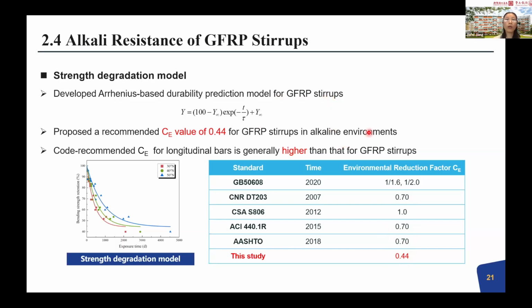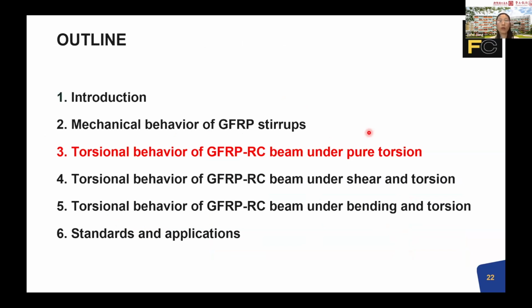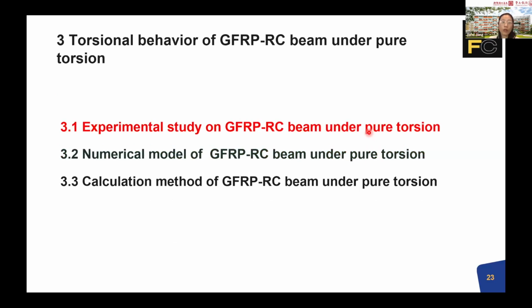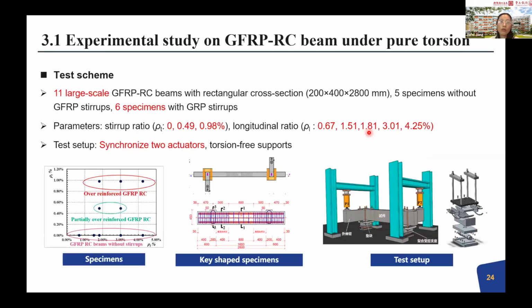So from the longitudinal behavior, no matter creep or alkaline resistance, our conclusion is that they have a significant difference to the longitudinal bars for GFRP. So when we finished the study of FRP stirrups, we now come into the members, first for torsion, and first, pure torsion. And we also finished the experimental study, numerical model, and also developed the calculation method for the strength. For the test, we have done 11 beams, which have rectangular cross-section, 5 specimens without stirrups, and 6 specimens with stirrups. The parameters shown on the screen include stirrup ratio and longitudinal ratio.